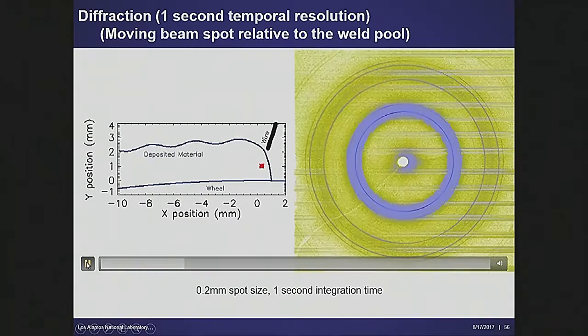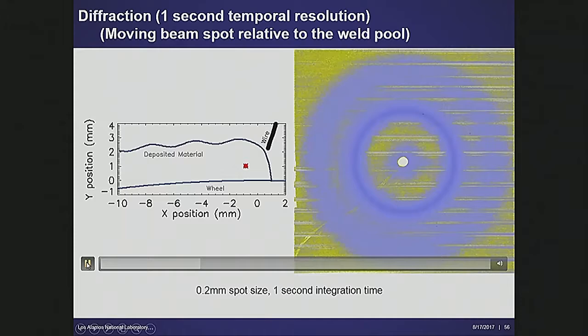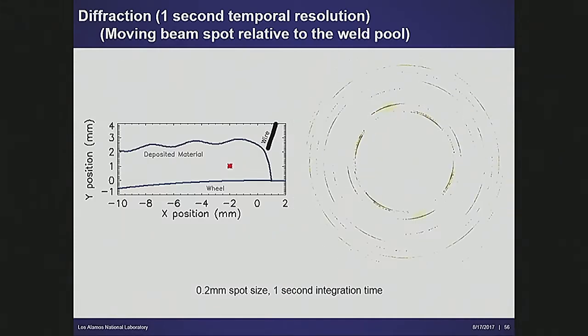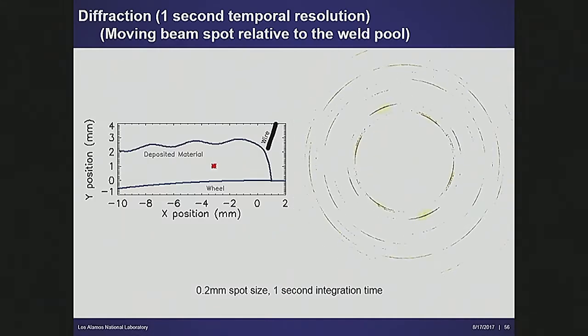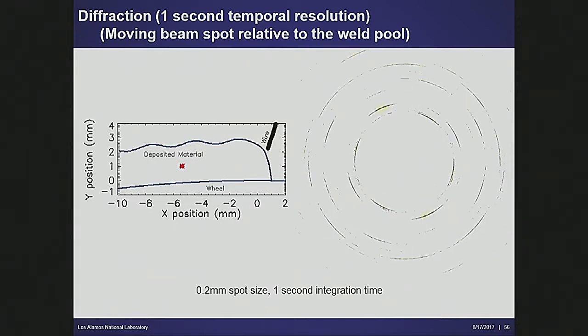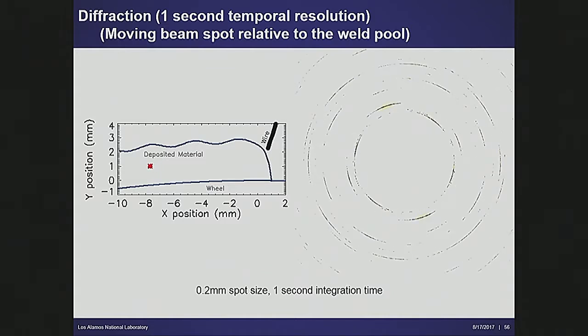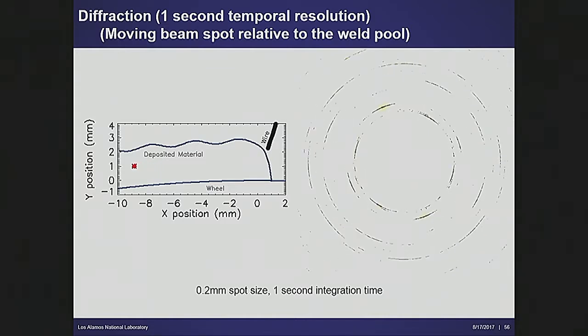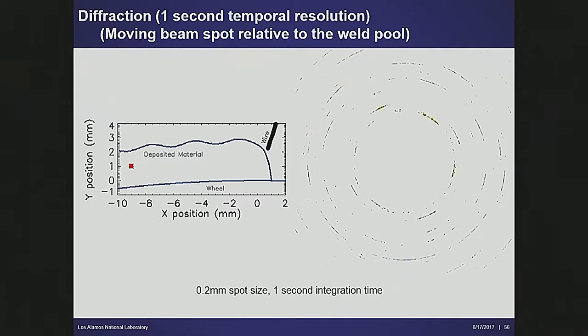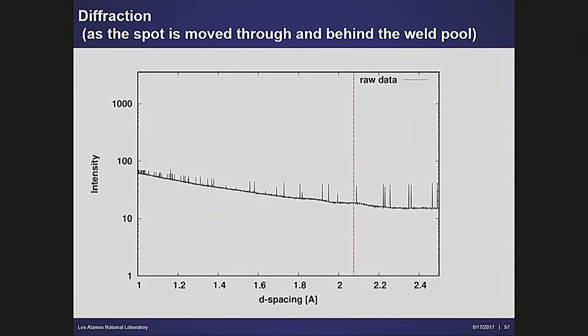We're dragging through, back here. Now, as you come back here, this is a second behind the weld front. This is a few seconds behind the weld front. The wheel is turning at a millimeter a second or so, so this is 5 or 6 seconds behind the weld. You can see that there's no longer molten metal here, and you've got a series of diffraction information on your transmitted diffraction detector.